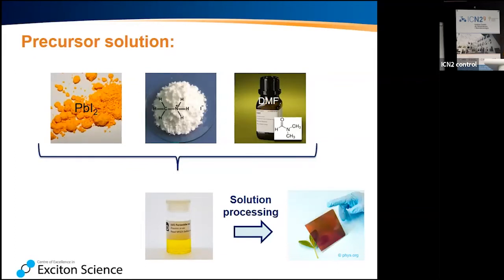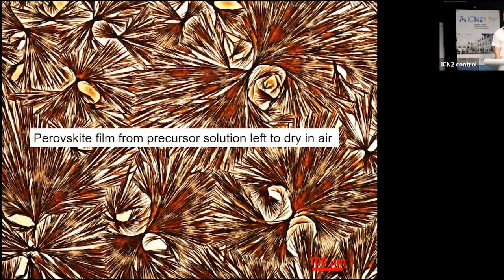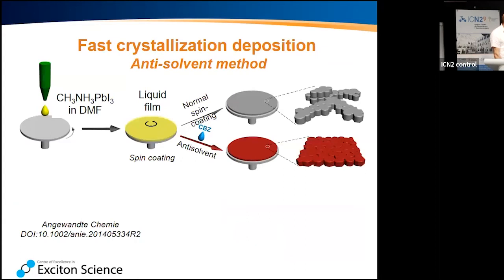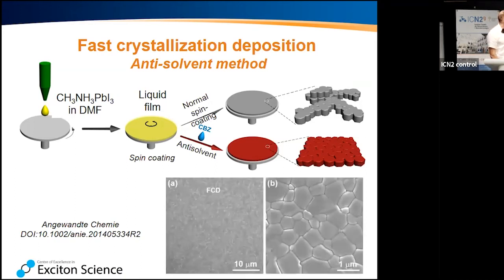Now, if you take your spin coating solution and you just drop it on a glass plate and let it dry, then you get something like this. It looks beautiful, but if you make a solar cell from that, the efficiency is maybe 1 or 2% or even less. So it's a very beautiful way of making perovskite, but not a very efficient one. What our group at Monash University used to do at the time, we were one of the first to come up with the anti-solvent method. In fact, we had a patent on the anti-solvent method at the time, and also on the next one that I'm showing you, the gas-assisted technique.